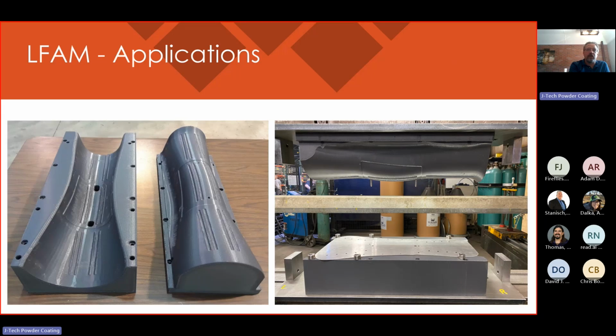This is short run production. They took a long time to print because they were done with a 0.6 millimeter nozzle due to the fine details. It probably would have been more economical to produce them with FGF to a near net shape and then clean up the surfaces in a 5-axis mill. Or actually, you could have done these in a 3-axis mill because they are all straight down. But this is a good example of short run tooling. They can actually run a few hundred parts with these PLA dies.